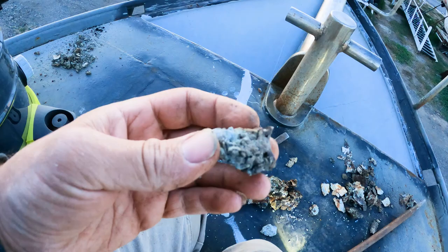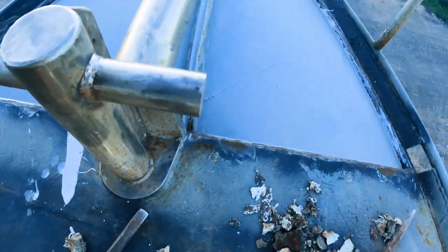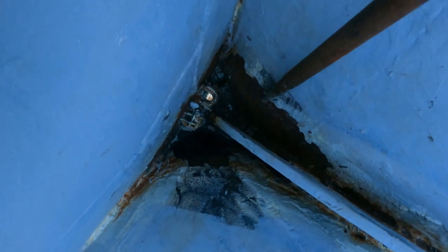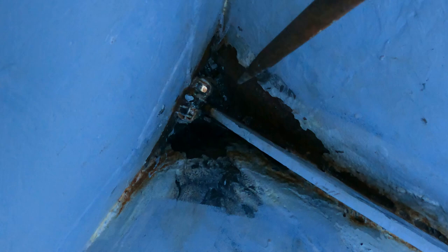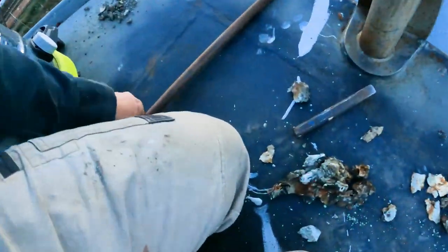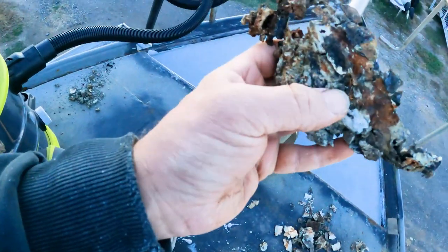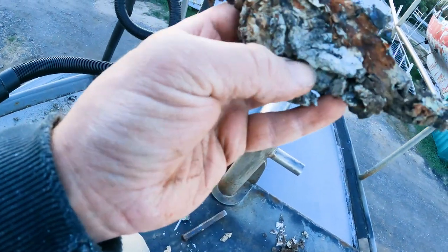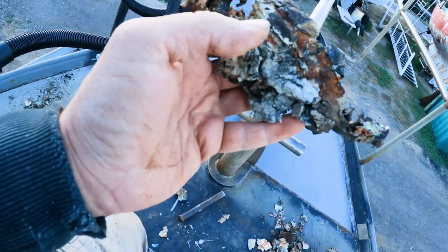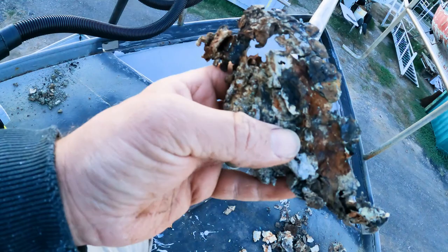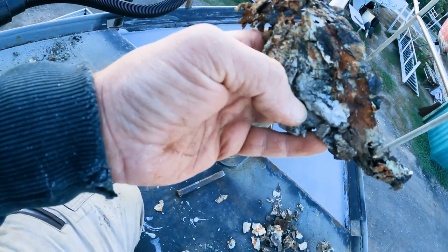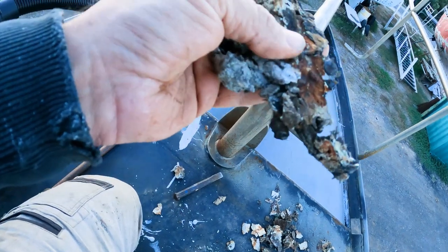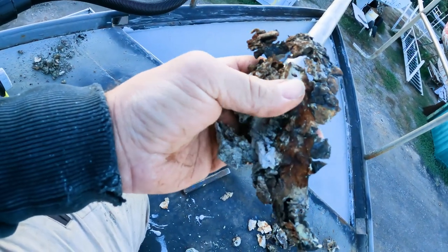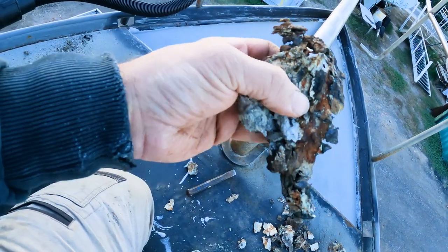So it seems that on the substrate, down here, down the bottom, there's been no painting, there's no coating. They've just poured the concrete or plaster straight on the bare metal there. So, as you can see, that plaster has been sitting up against the bare metal with no coating in between it. So they've used the concrete substance, whatever it is, as the corrosion protection. As I can feel this, it's actually wet. It's been soaking in the moisture. So this is pretty bad.